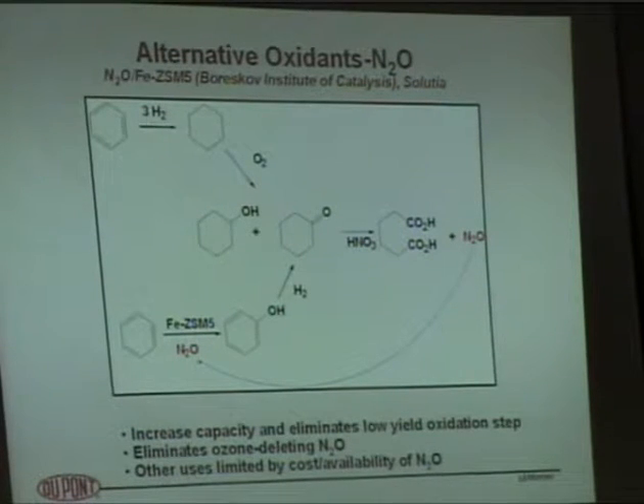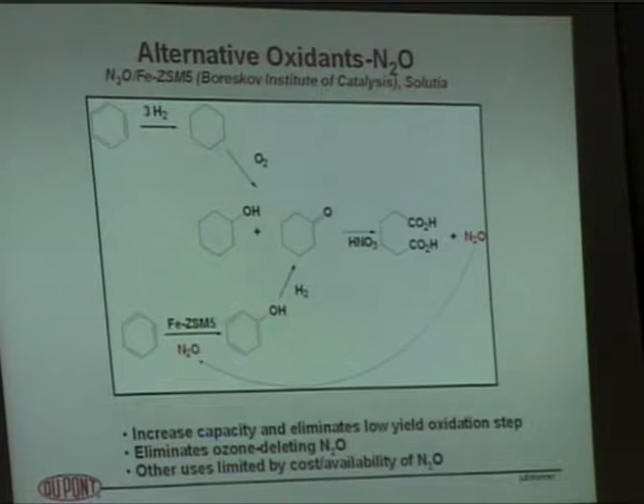So all of the nylon 6 and 6,6 producers got together and agreed to reduce N2O venting by one technique or the other. We decided to take the easy approach, which wasn't so easy, but just to decompose N2O back to nitrogen and oxygen. That's now commercial at all of our plants in the world, so we've taken care of that problem. Solutia decided, and this was the right decision, to use that nice source of activated oxygen. You've got N2O here, and why not use it to react with benzene using the Panov catalyst to make phenol, which you can then convert to cyclohexanone and nitric acid oxidize it.